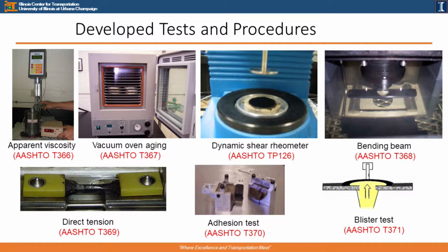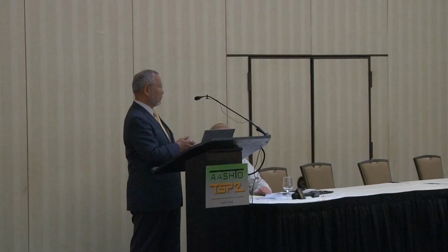And then for the Superpave asphalt binder specification, they use the rolling thin film oven and pressure aging vessel. But instead of RTFO and then PAV, they developed a so-called vacuum oven aging system. And then they use the same DSR as asphalt binder. And also they use the same bending beam rheometer.